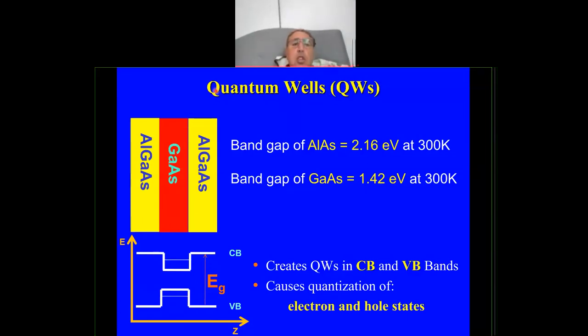So we just use two semiconductors with high energy bandgap, like aluminum arsenide, aluminum gallium arsenide, and we sandwich gallium arsenide between these layers, which has a low energy gap. And that's what we have in this energy profile as a function of Z. This is Z. Now here, going from this to that.